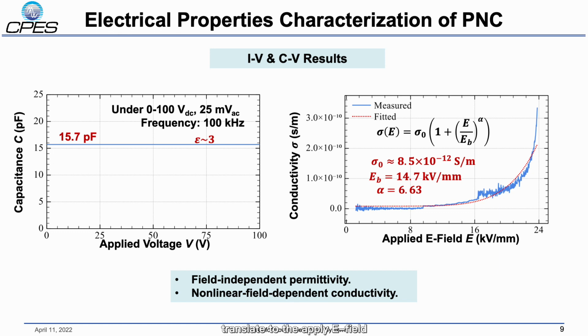translate to the applied E field versus the conductivity. We can see the blue curve is the measured curve, and the red dot is the fitted curve. We use a formulation usually used in the references to fit the curve, and here are the fitted values. These fitted values are within the range we previously found in the simulation paper. So this should be the desired properties for medium voltage power module field grading applications.